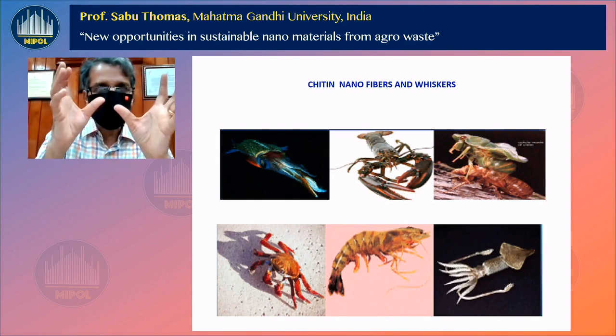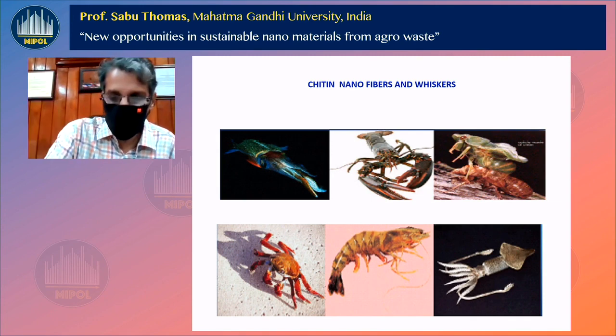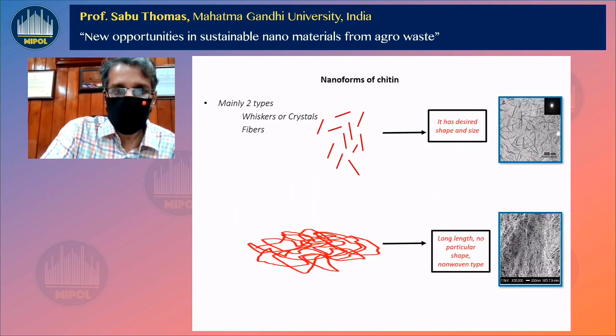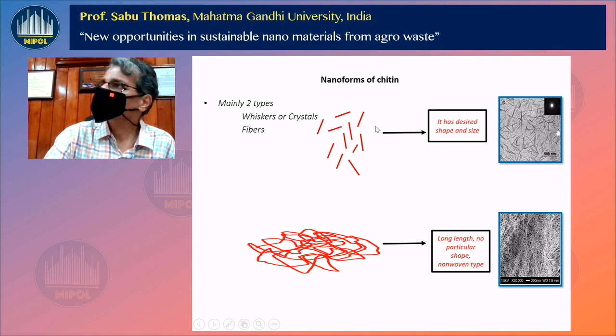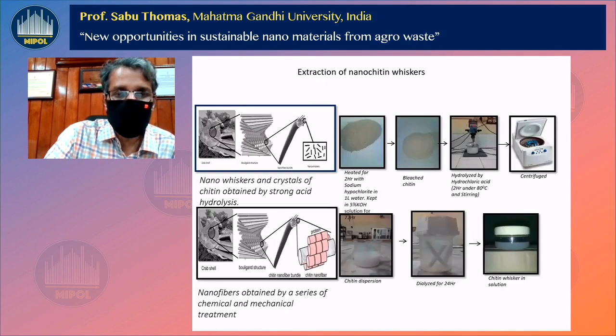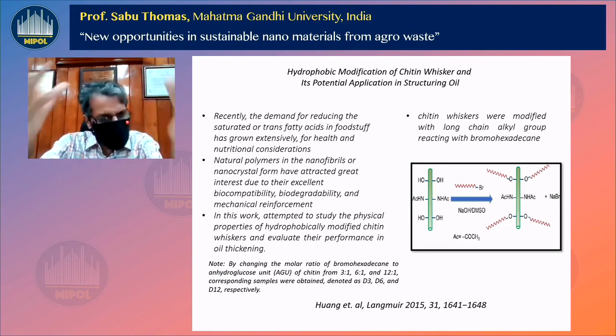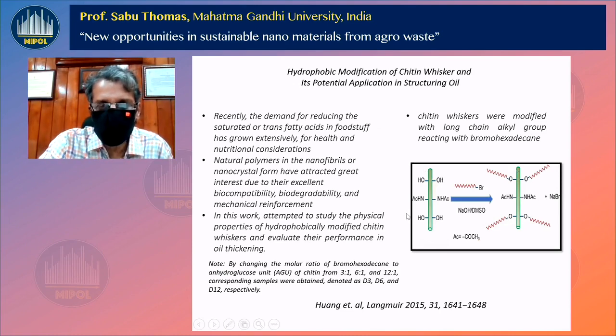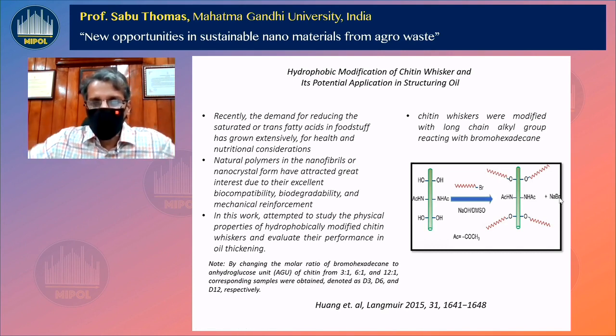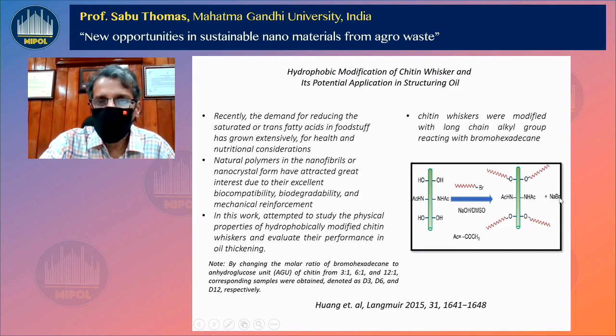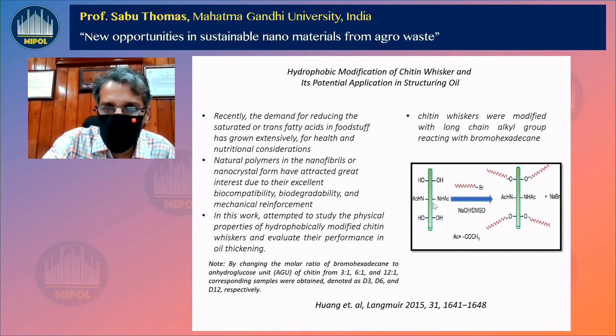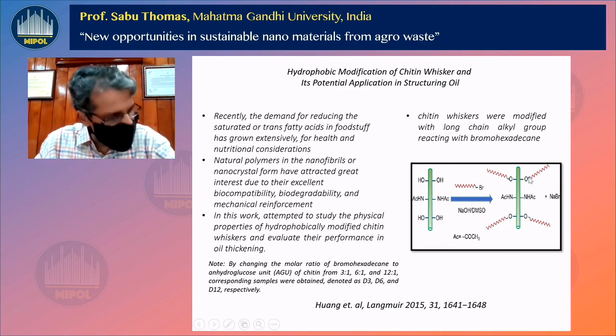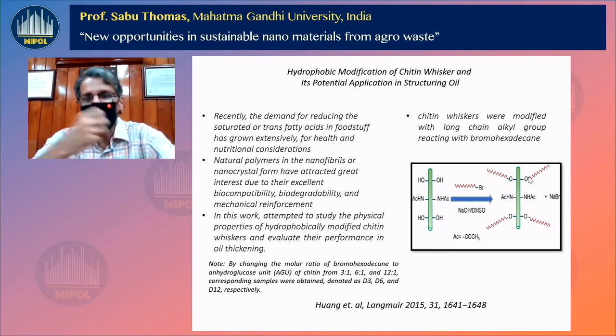We are also active in chitin and chitosan, extracted from crab shells. You see, we can make either chitin nanocrystals or nanofibers, by acid washing and steam explosion. I will show you one work. Nanochitin is essentially hydrophilic. This is the structure of nanochitin, with a lot of hydroxy groups. And you can introduce an alkyl group on the surface of nanochitin by simple chemistry. You react with bromohexadecane, then you can have this sort of alkyl group. If you put an alkyl group, the chitin becomes hydrophobic.